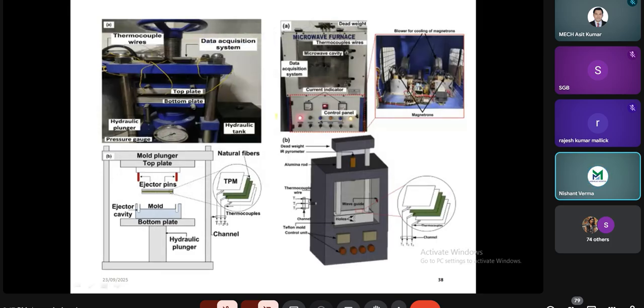So what we did: this is the laboratory level setup of the conventional compression molding, but it was sufficient to prove our study. This is the top plate, bottom plate, and hydraulic plunger; the whole thing is made to make the composite. We took the polymer sheets as well as the fiber sheets, and we took a thermocouple and inserted it between two polymer sheets, two fiber sheets, and the bottom one again a polymer sheet. We replicated similar things in the microwave.